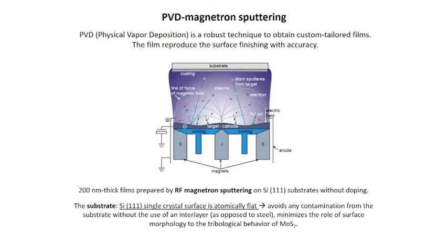Okay, in order to generate this film, we use the physical vapor deposition magnetron sputtering technique. Here you can see a sketch of the machine. In this case, the material is deposited in a vacuum chamber where you have the target, which is composed of MoS2, and the substrate in the top part of the chamber. By inducing a plasma and sputtering of the plasma on the target, you have the generation of a flux of molybdenum and sulfur atoms towards the substrate, and the condensation on the substrate generates the final film.